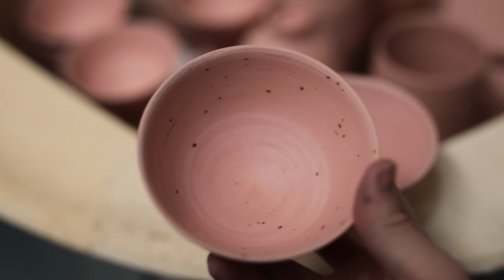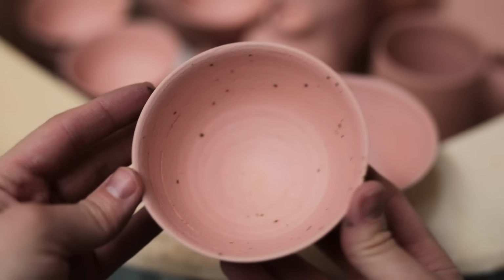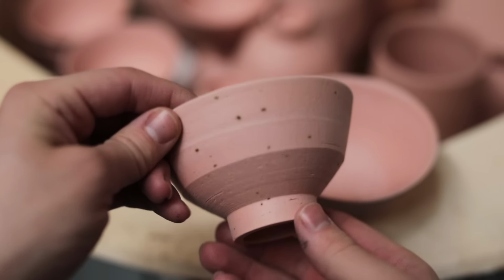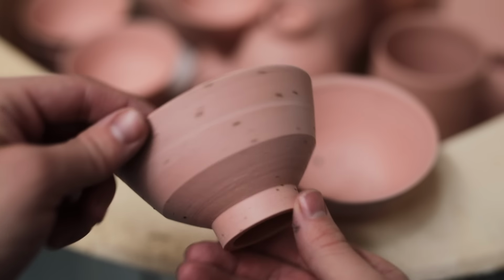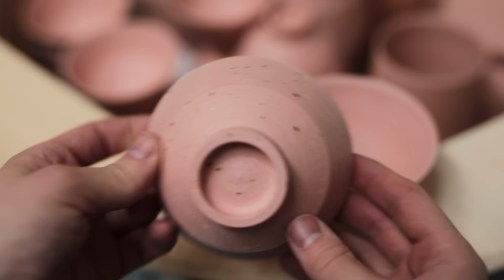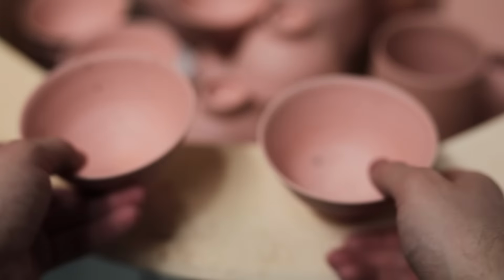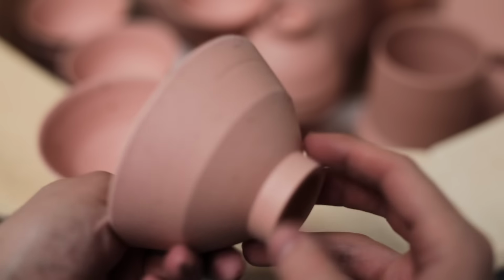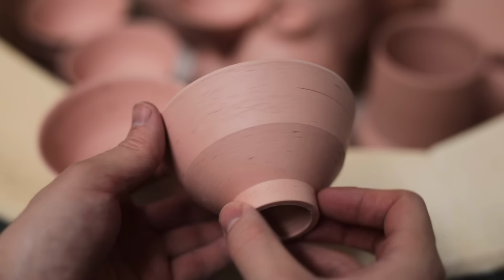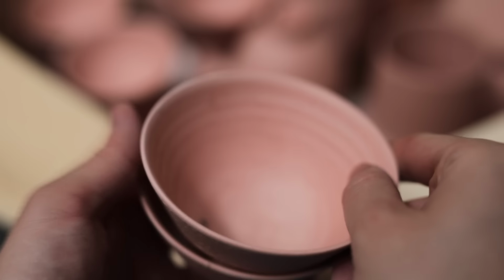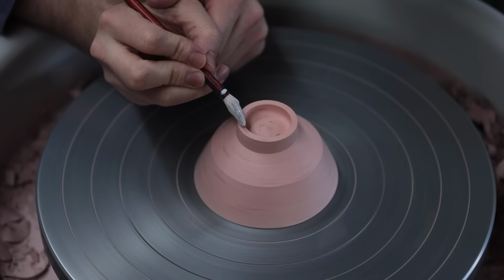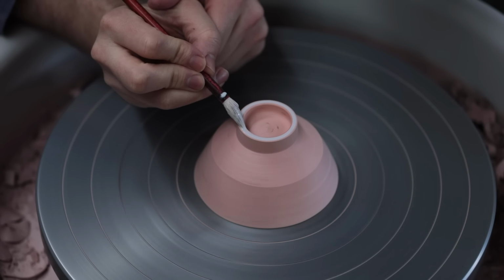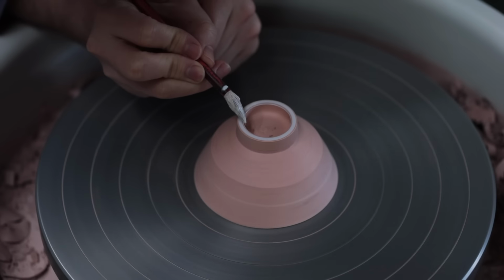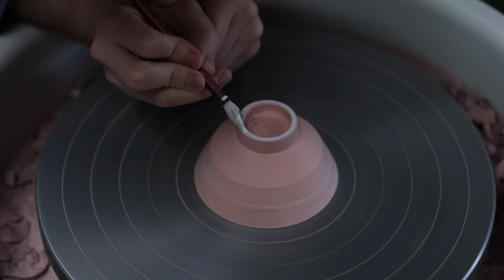And here they are. The bronze to begin with, the metal inclusions just beginning to melt. The clay around them looks singed, but I honestly thought they would melt and move a lot more than this, so I'm happily surprised. Next, the steel hammer scale, which you can barely make out, save for a few larger flecks. Before I glaze these, the feet of each is waxed. This acts just like a wax resist, preventing the glaze from adhering to this area, meaning I have to spend less time tidying up each pot after they've been dipped in glaze.